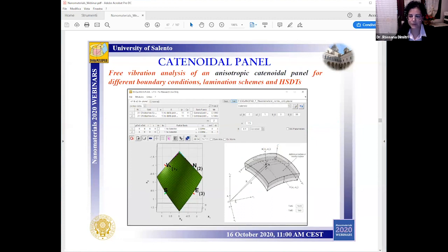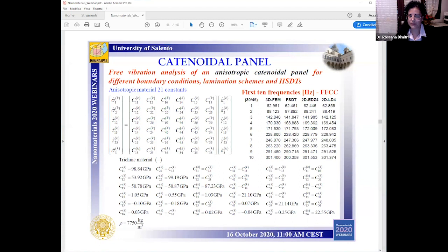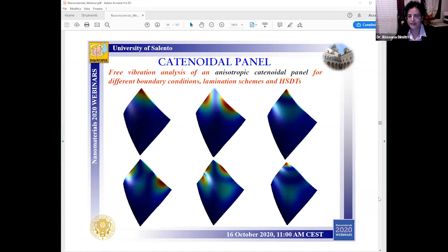example, we analyze the free vibration of an anisotropic panel for different boundary conditions, lamination schemes, higher order formulations and theories, where we can cut the undistorted domain using a rhomboidal shape. And where we show first the accuracy of the numerical method and proposed formulation by comparing the first 10 frequencies for a lamination scheme 30-45 degrees as provided by the first order shear deformation theory and higher order theories against the 3D FEM based approach from commercial codes. So we have used Abaqus in this case. With a very good agreement between results, and here are the related mode shapes for the selected boundary condition.